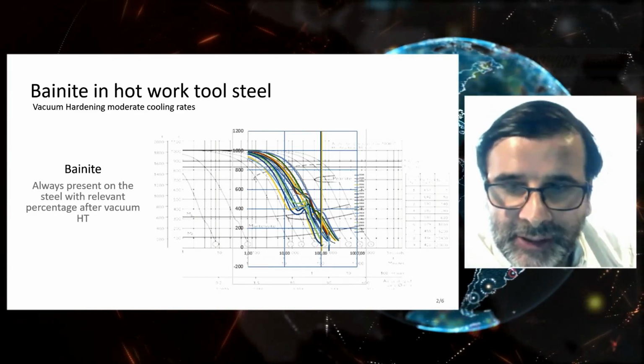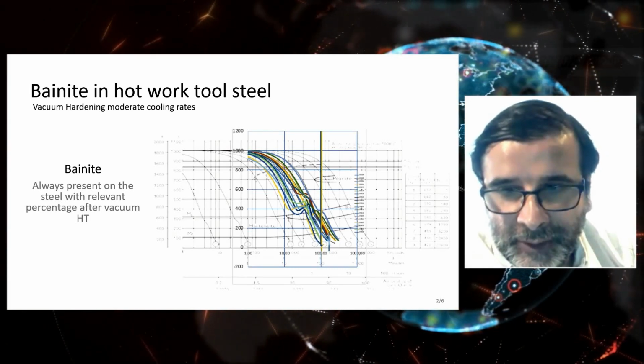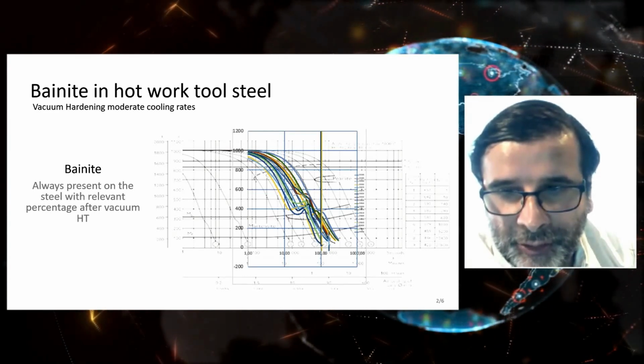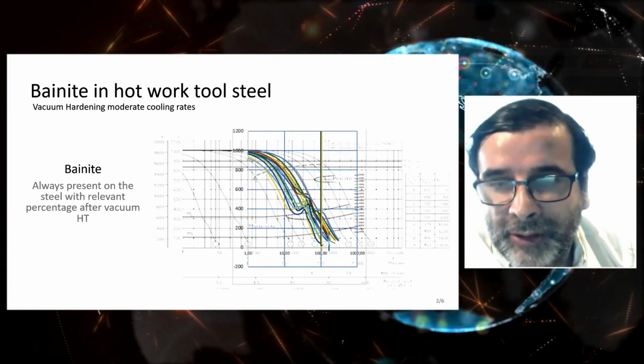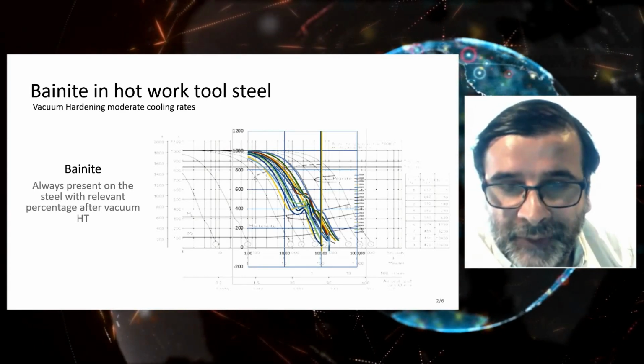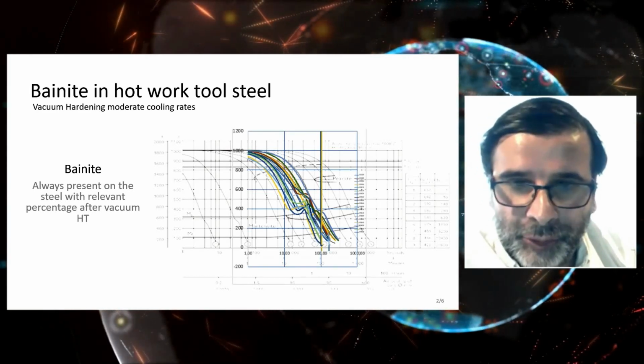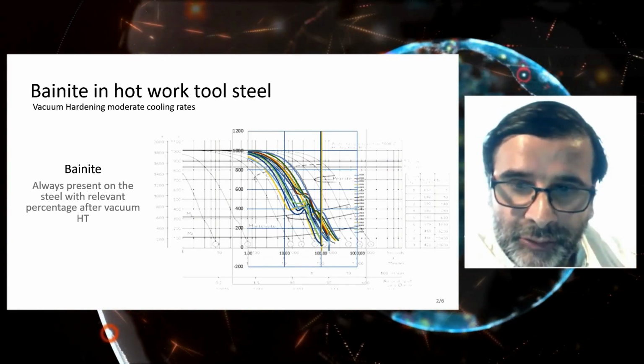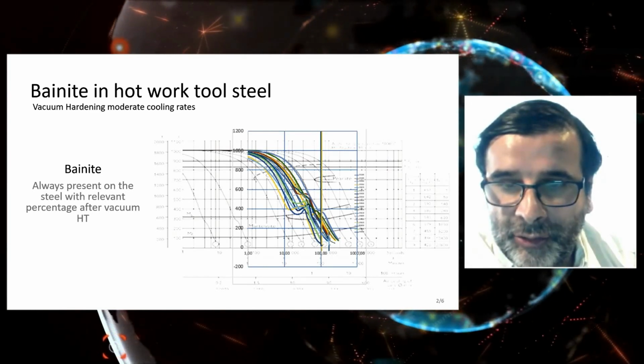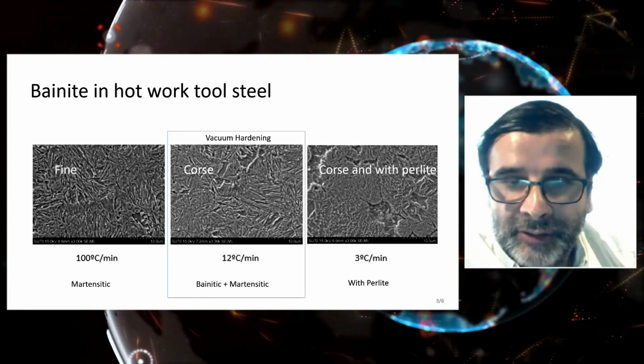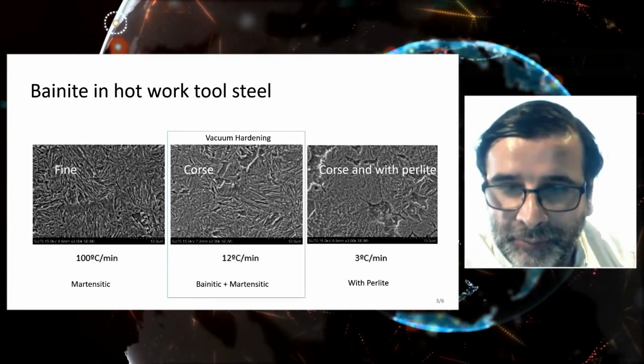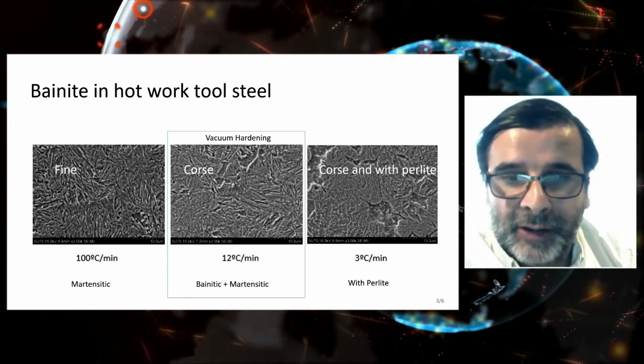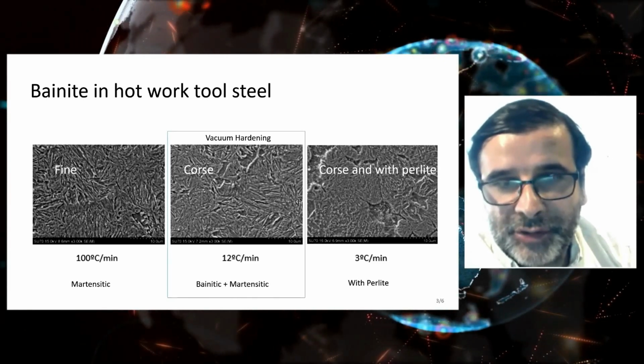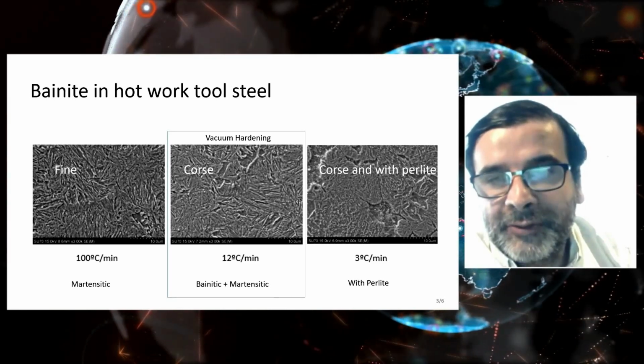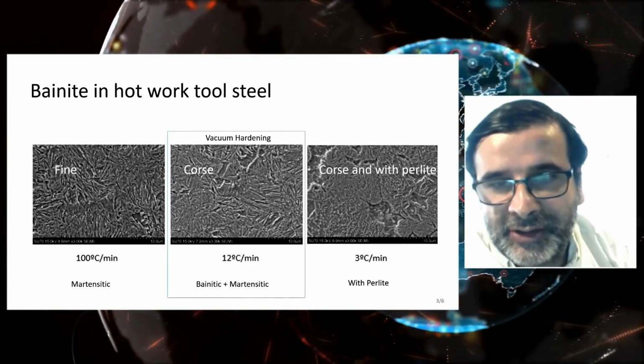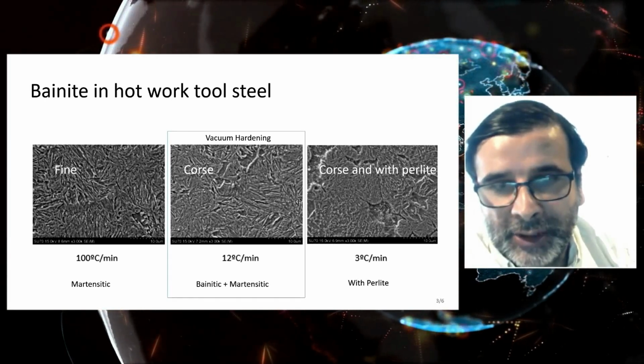So basically, the hardening furnaces will introduce cooling speeds on the parts that will always produce a certain amount of Bainite. This occurs mostly for hot work tool steels, because the parts are not so thin as in cold work applications. The thickness of the die casting molds is bigger, and this means that cooling speeds in vacuum furnaces are not so fast. So this will introduce a certain amount of Bainite to the microstructure, and 12 Celsius degrees per minute is a typical value for cooling in vacuum hardening furnaces.